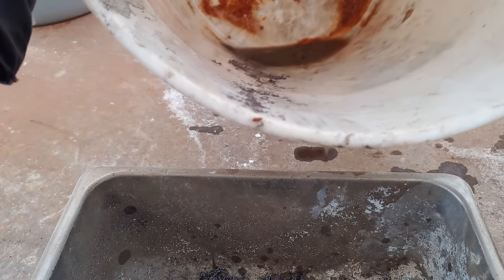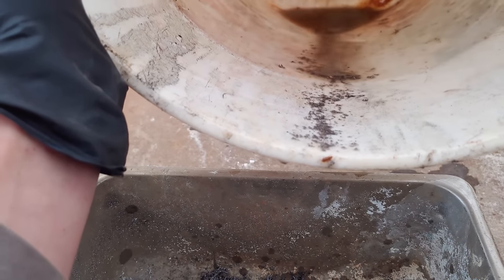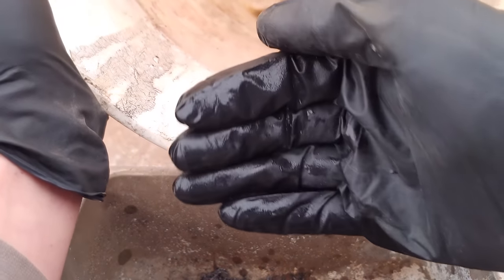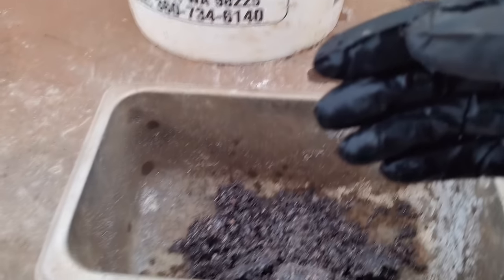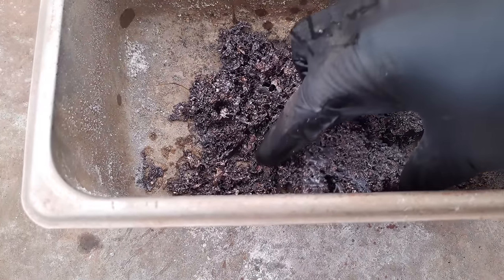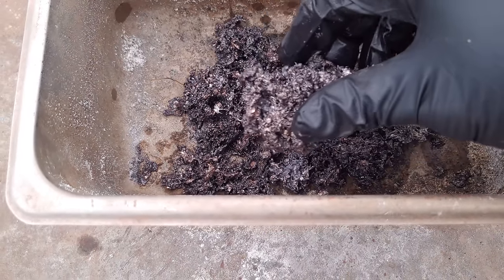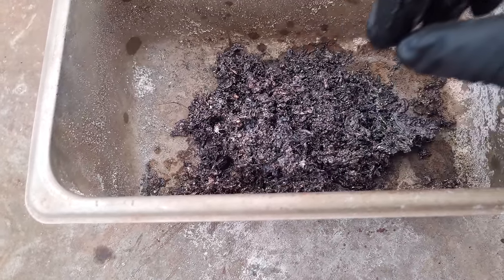because we have a huge amount of surface area on the lead, I can add a bunch of oxidizer and oxidize the lead and the copper and the base metals, all the junk in there we don't want. And all the precious metals will collect at the bottom. And then we'll have a much smaller button to work with. We don't have to cupel 500 grams. We might have to cupel 50 or maybe 20. We'll see what we come up with.